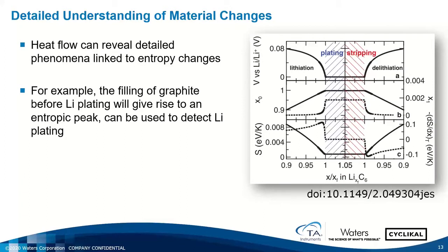Another thing that can be done with isothermal calorimetry is looking at the details of what's happening at the material level. Often there'll be entropy changes in a material that will give you signatures in your heat flow. An example of this is lithium plating. When graphite is filled, as its voltage drops towards zero, all the layers in the graphite get filled and all the lattice positions are occupied by lithiums. As this happens, the entropy drops. When I place my final lithium atom, there are no more configurational states available to me, and so my entropy is dropping. And then when I start plating, my entropy becomes constant.